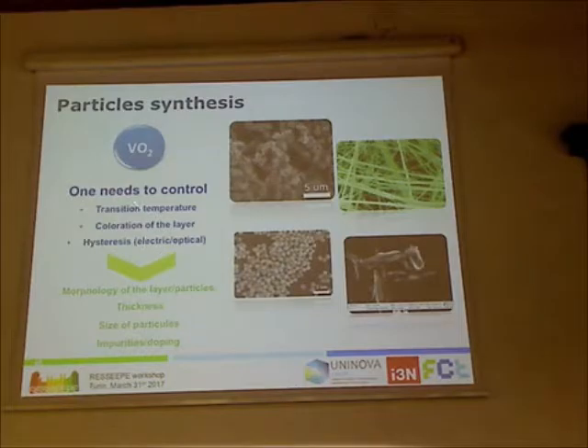So how can you control this? You can dope, controlling the transition temperature by introducing some dopants in the VO2. You can control the hysteresis and also slightly adjust the transition temperature by changing the morphology or the size of the particles. Of course, the coloration you can control by changing the thickness of the materials.